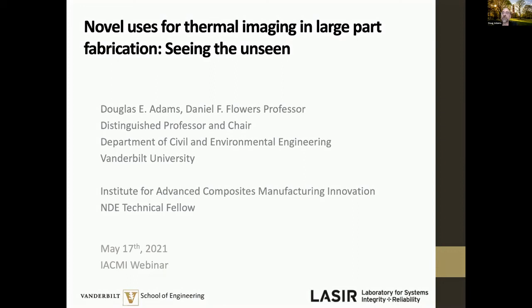The idea would be to stitch those thermal images together by piggybacking on the equipment that's already used. The advantage, of course, is it's full scale and line of sight. As long as you can get line of sight of the mold, you're able to utilize these images. You would also have to think about how you select your cameras. You'd want enough pixel density so that if you have a flaw size that is unacceptable from a design standpoint, you span that maximum acceptable flaw size with enough pixels to ensure a high probability of detection. That's a matter of picking the right camera, but also the right distance you are imaging the material from, because the closer you get, the more pixels you put on the surface.